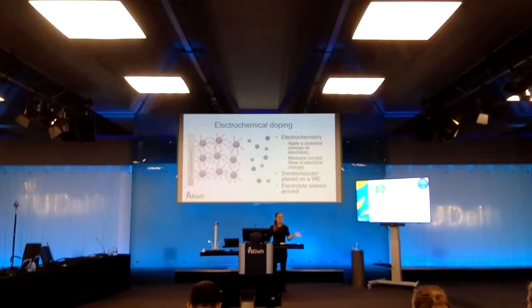So what we do in electrochemistry is that we apply a potential. And what that means is that we control the energy of electrons in our conductive substrate. Then we measure the current, and current is just flows of electrons. So basically we apply different energies to our electrons, and we see if they flow out of this conductive substrate, or if actually the conductive substrate gains more electrons. And that's basically electrochemistry in simplistic terms.